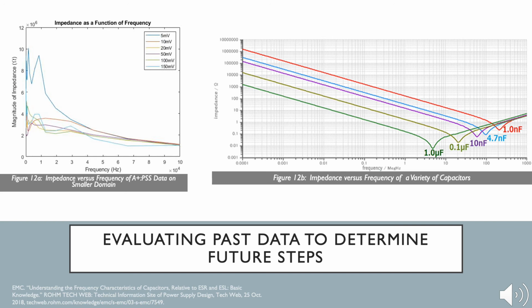We then evaluated the composite with the 1:1 volume ratio of PEDOT:PSS, also known as A plus PSS, for their experiment. To introduce the data, there were 6 trials at different source voltages, and with the sinusoidal nature of capacitors and alternating current, the resistance, impedance, frequency, and current were measured.